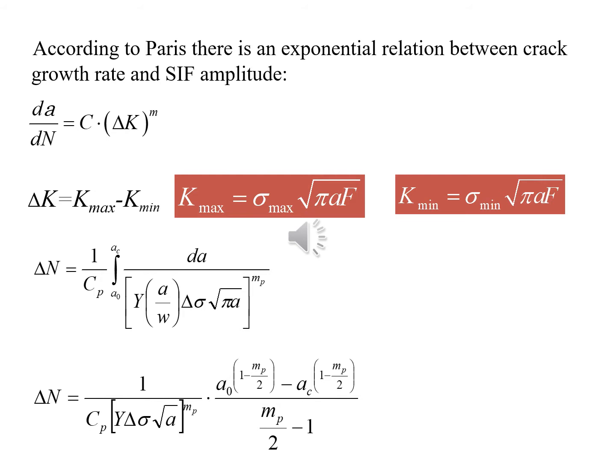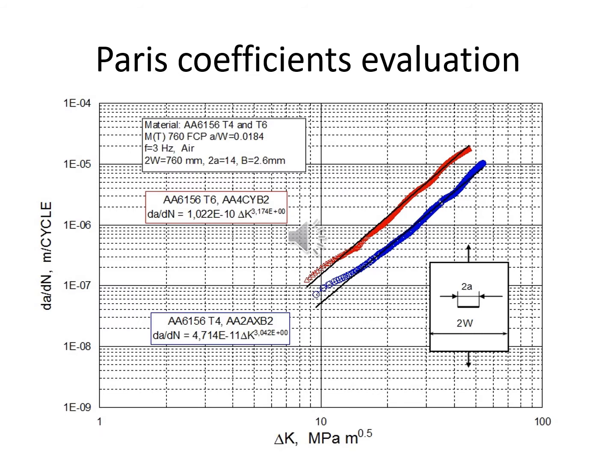Once we mentioned fatigue, Paris law is next issue to consider. So the famous exponential relation between crack growth rate and stress intensity factor amplitude is also considered here, both experimentally as a part of fatigue testing and then later on numerically. 2 different materials were tested, both aluminum alloys but differently treated. You can see here in red and blue results for 2 of them. You can see that blue one is definitely better in the respect of fatigue crack growth, because both coefficients of Paris law are lower or slightly lower in that case.